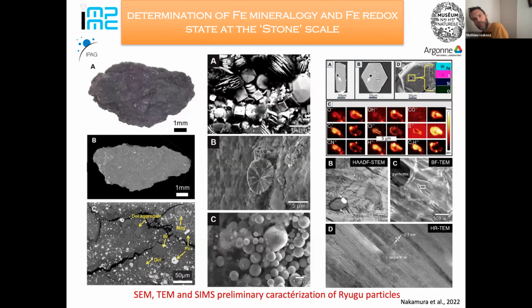And then if you look at the mineralogy with the SEM, TEM, and tomography, this is more or less what has been reported in the first papers published. So the grains are relatively small, a few tens of microns. The mineralogy is dominated by magnetite with different shapes. So you have rhomboids like this, and you have platelets. Now we know that there are at least two formation ages for the magnetite. The two different textures correspond to two different environments or two different histories of the asteroid.